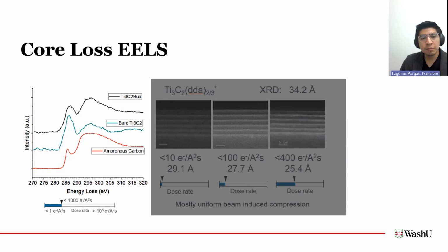And so the carbon signal should only come from the titanium carbide. And you can see we have a peak around 286, and then a broader shoulder that extends with its maximum peak around 296. Or sorry, the 286 is the first peak, and then the broader second peak is around 296. And then we would expect that the spectra from the hybrid MXene would show this bare MXene peak overlaid with additional peaks coming from the organic surface groups.